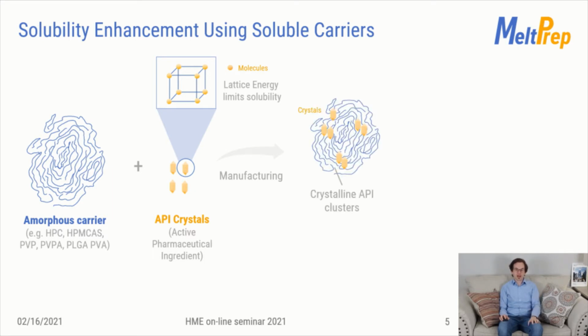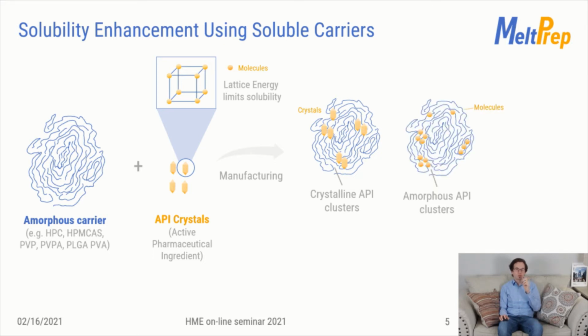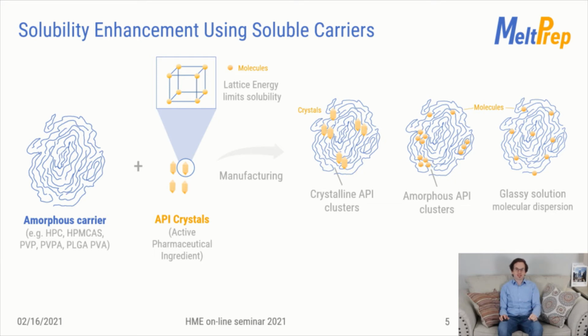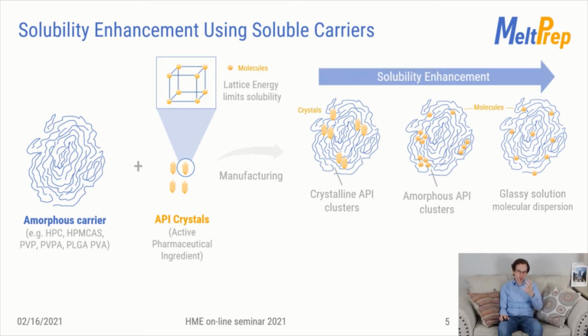So crystalline API clusters within an amorphous carrier, or molecules closely arranged in amorphous clusters, which are embedded inside the polymer, or the most preferred option for solubility enhancement is a glassy solution. In this case, single molecules are well distributed in the polymer, there is simply no lattice energy to overcome. The API release will follow the release behavior of the polymer. When the polymer dissolves, your single API molecule will just drop into the dissolution media and will be available for the body.